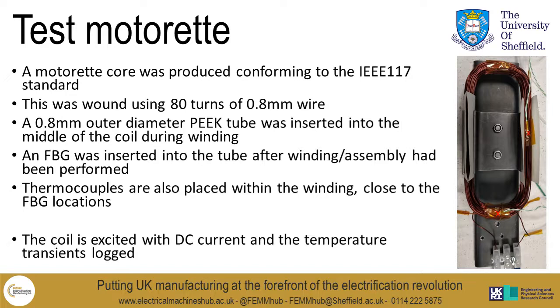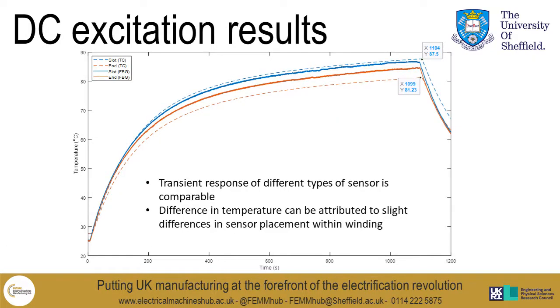To actually test the sensors, we heated up the coil by applying a constant DC current to it, and logged the temperature during the test. This slide here shows the results of that testing, and what you can see, the dotted lines represent the thermocouples and the solid lines represent the FBGs. You can see there's not a great deal of difference between the sensors, and the transient response time is very comparable between them. There are some slight differences between the sensors, but that can primarily be attributed to the slight difference in placement within the winding.